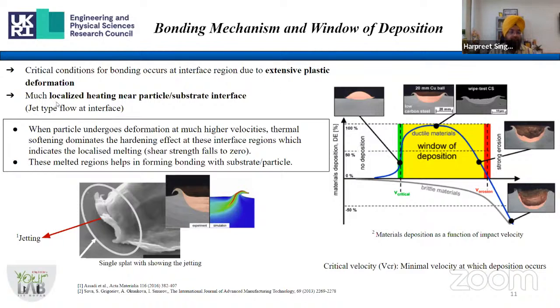So that we have much localized heating near the particle substrate interface. If you see here, usually this jet type of flow occurs at the interface. It is being modeled by several people now, on how this particle comes and then how it is sticking on the surface. So when the particles undergo deformation at much higher velocities, when the particle comes, it will strike on the surface, and there will be localized heating along the interface, and that heating will dominate, or it will result in softening of this particle.